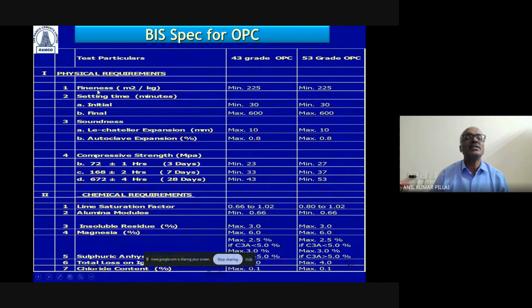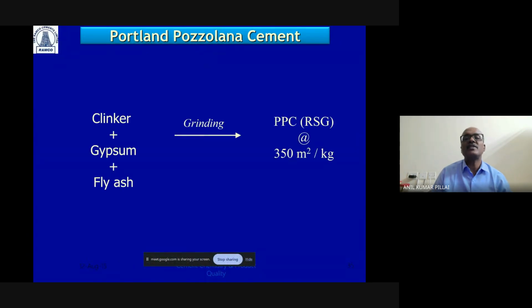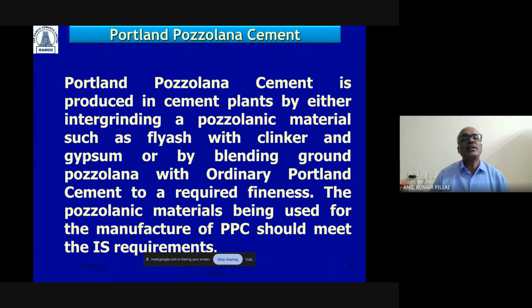So as a customer, if you are given this cement test report, you get a fairly good idea of what the physical requirements of cement are and what the chemical requirements are as per the code and as far as the particular cement is concerned. So this is what you will find: clinker, gypsum and fly ash are ground to give you Portland pozzolana cement. And even in Portland pozzolana cement you can get a cement of higher compressive strength by changing the chemistry of clinker, as well as the chemistry of cement itself and the way it is ground. So that is why you will find that even in our own Portland pozzolana cement, there are various types in terms of strength gaining properties. If you want a PPC with only low heat of hydration, you can go for it. Or if you want a PPC having low heat of hydration as well as higher compressive strength, you can have a cement manufactured based on that. So this is what it is all about.